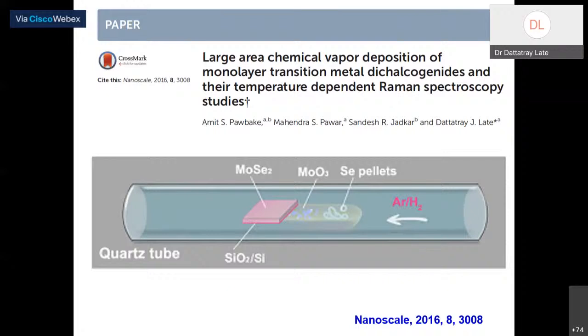So once we have this, depending upon the temperature, because we need to evaporate both sources, selenium and MoO3, at the same temperature. Because selenium's melting point is around 220 degrees Celsius, and MoO3's evaporation point is around 450 degrees Celsius. We have to evaporate both materials at the same time, with hydrogen as a reducing agent. So we'll be able to convert MoO3 and selenium into MoSe2, or MoS2 depending upon what we want, and all these things. So you can choose the salt or precursor depending upon that.